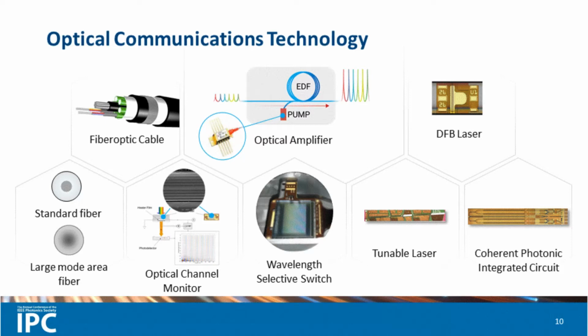For one, the transmit laser center wavelengths needed to be carefully controlled, and so periodic refractive index profiles interacting with the diode laser cavities were introduced to lock the diodes to specific wavelengths. Additionally, thin film filters with many layered dielectric stacks were developed to select one wavelength out of the set of many wavelengths. Tens of thousands of hours of careful materials engineering went into these types of devices to balance stresses, reduce defects, and improve yields to commercially viable levels.